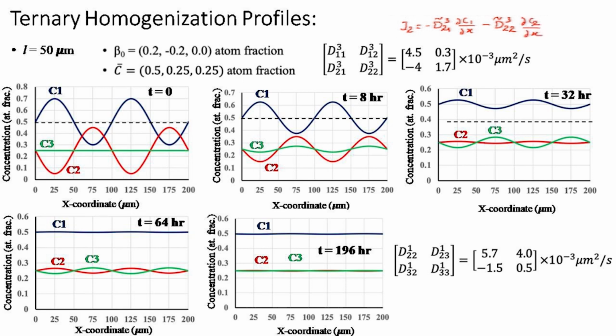The gradient of 2 is also high to start with. So, both the gradients are high and C1 is flattening out very fast. So, the interaction effect of 1 and 2 is not very obvious here, and by the time C1 has flattened out, the gradient in C3 has picked up, and so the interaction of 3 on 2 has come into effect.